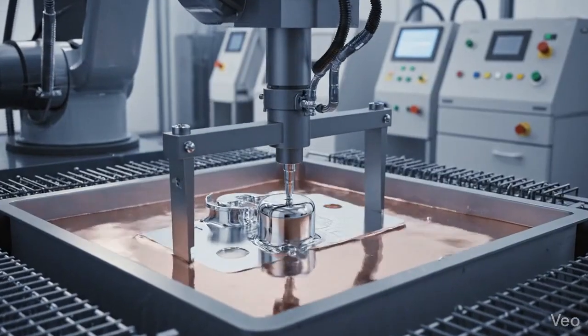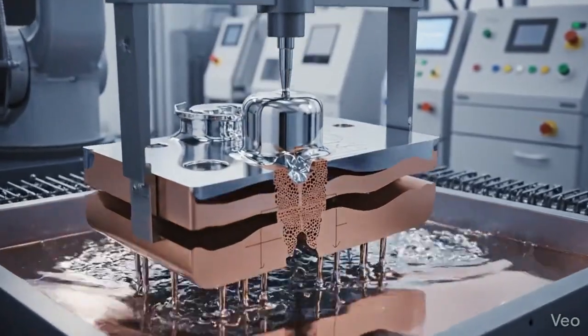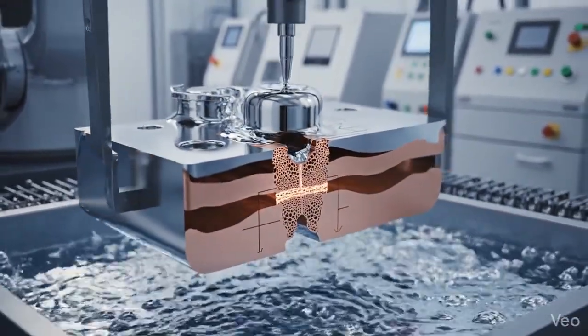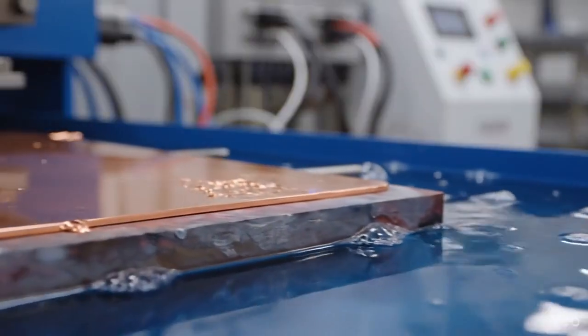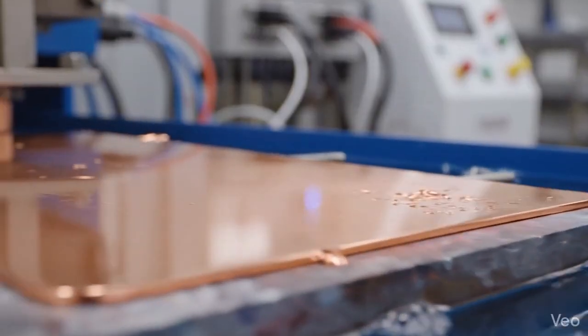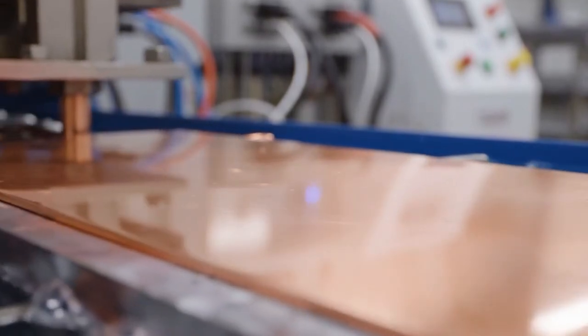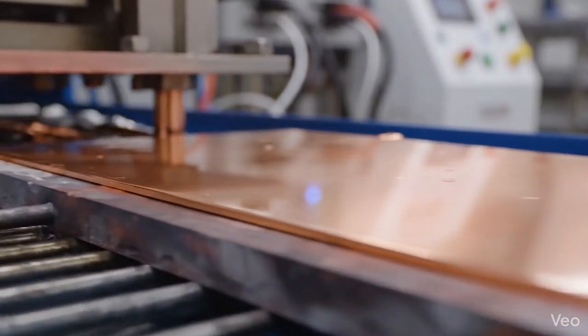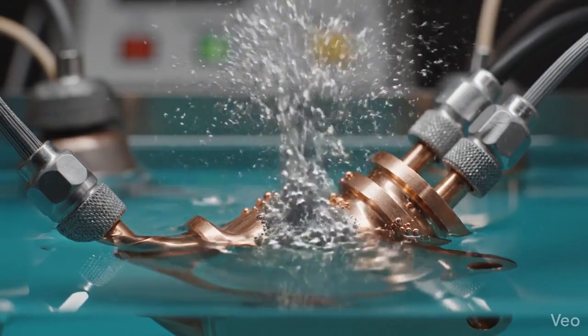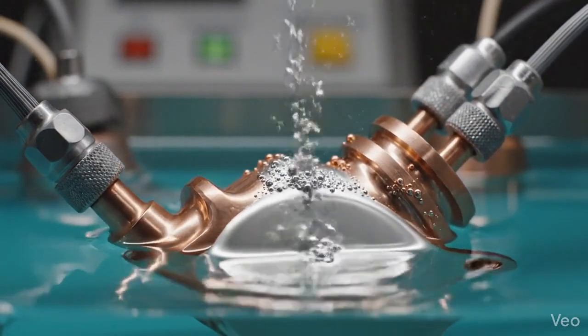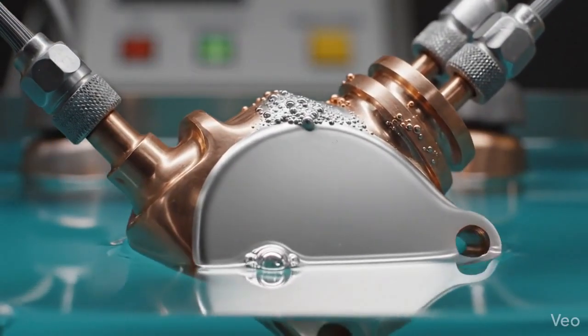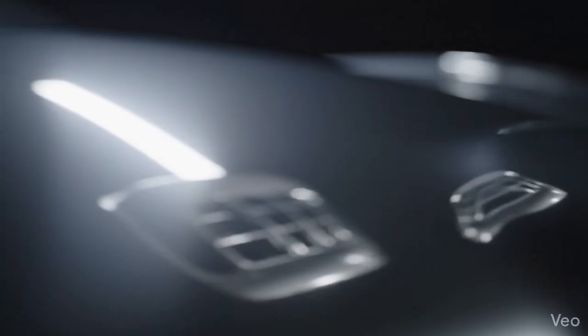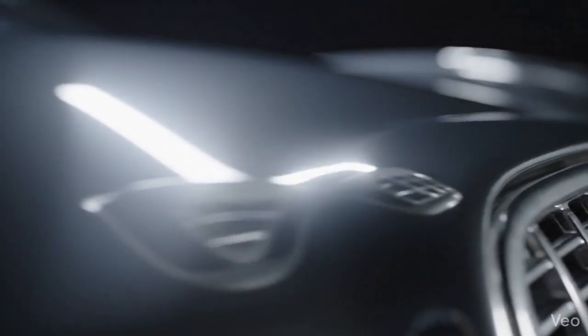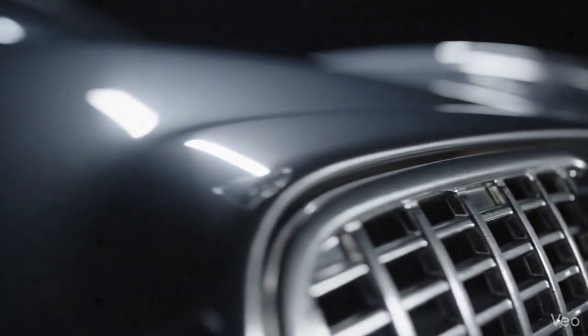The traditional automotive chrome plating process involved three stages built on top of one another. First, a copper undercoat was applied to create a fully conductive, pore-free base layer that covered any microscopic surface irregularities in the base metal. Second, a nickel layer, typically a dual-layer system with semi-bright nickel followed by bright nickel, was deposited over the copper. This nickel layer is where most of the actual corrosion resistance of a chrome finish resides, and the quality of the nickel work determines how long the finish lasts in the real world.